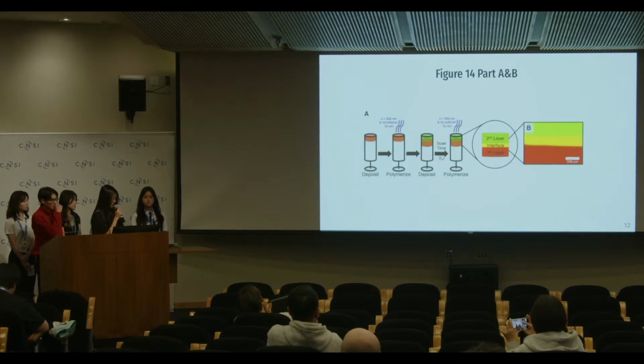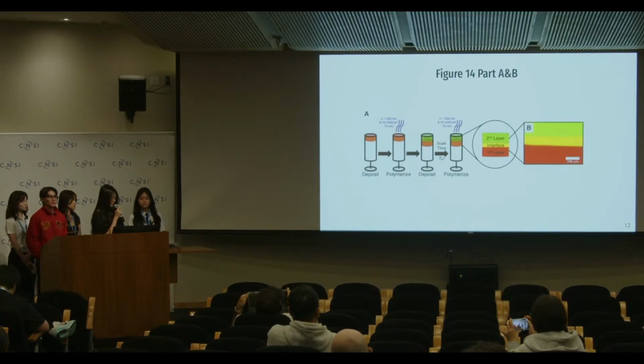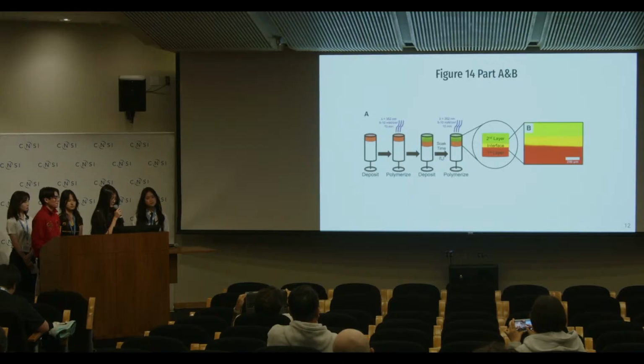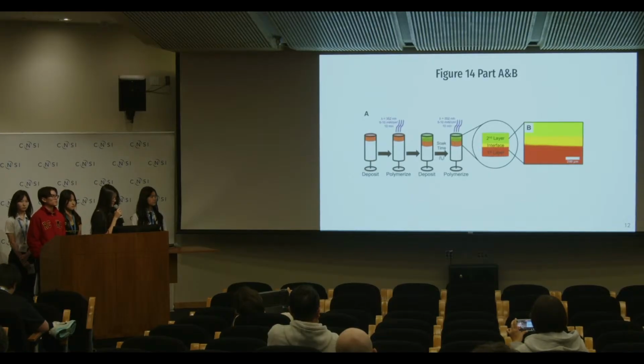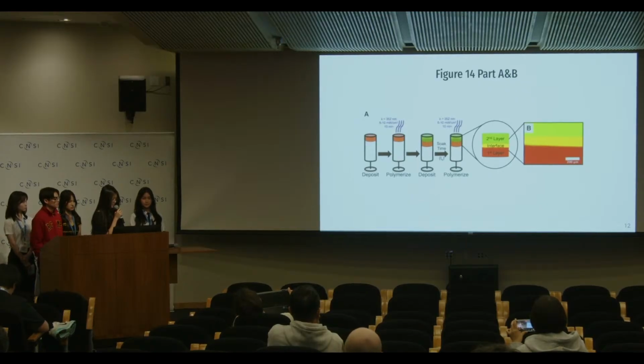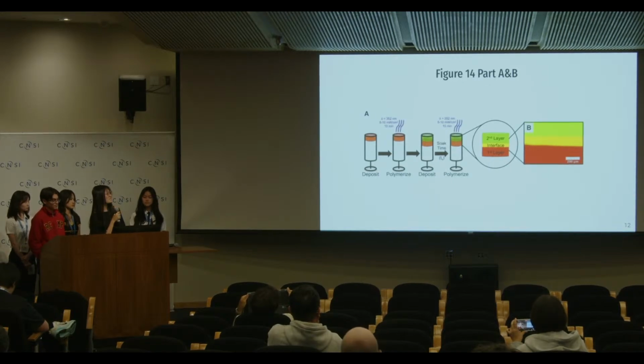And B shows two things. First is a confocal laser image where different fluorescent dyes prove the two layers are in the right place. And the second is an AFM mechanical map. This map is built exactly the way I just described, one force distance curve per pixel. Darker colors mark the soft top layer, and the brighter colors mark the stiff base. So because the AFM converts cantilever bends into force and then force into modulus, it gives solid quantitative proof that fabrication worked.